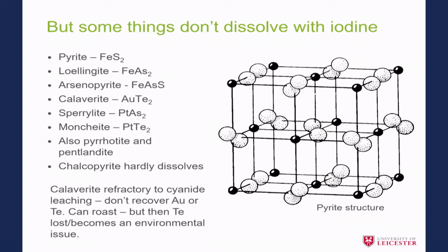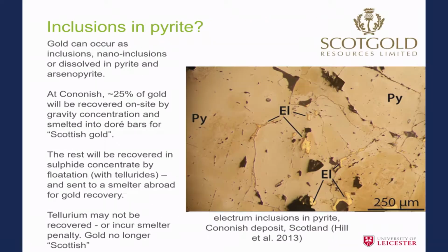And calaverite is a big issue because it doesn't dissolve in cyanide and is often a cause of gold going to waste, because it is not leached by cyanide. You can roast it, but then you have to deal with the tellurium, and it's an environmental issue. Now we'd like to recover both the gold and the tellurium. And of course, sometimes gold occurs in very fine inclusions in pyrite, sometimes even dissolved in pyrite, and then of course you need to break down the pyrite structure to liberate the gold.